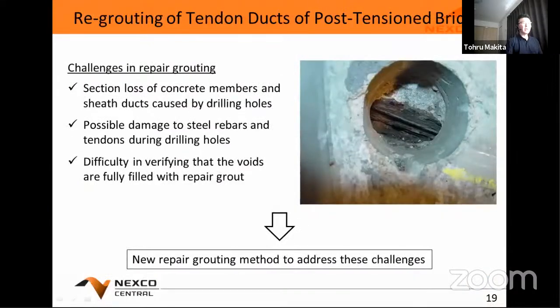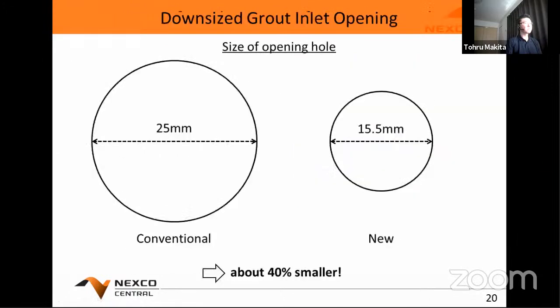But there are some challenges in repair grouting. In order to inject repair grout, it is necessary to open grout inlets by drilling holes. But it causes section loss of concrete members and sheaths. And during drilling holes, steel rebars and tendons might be damaged. And after finishing repair grouting, we need to check if the voids are fully filled with repair grout, but it is very difficult. In order to address these challenges, a new repair grouting method was developed.